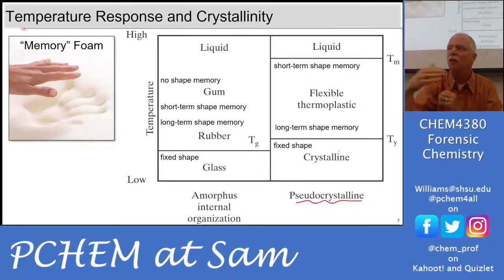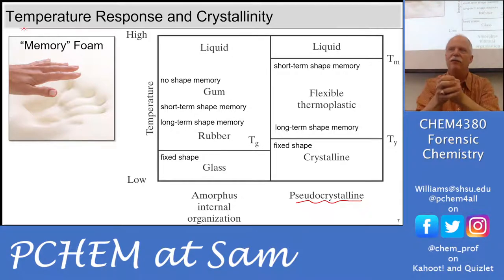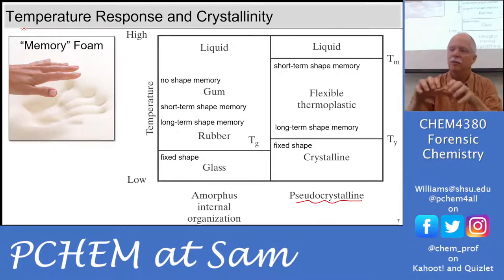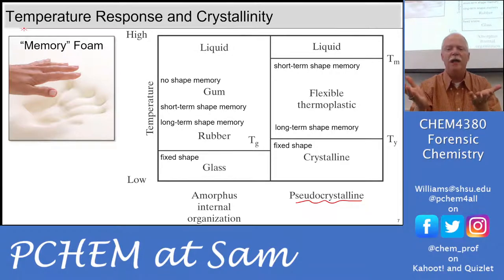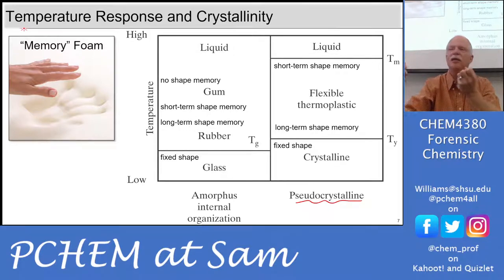The crystallization happening slowly over time is something we'd like to prevent in a lot of plastics — once that crystalline phase starts to grow, it becomes very rigid. We don't want rigid plastics because they crack. This is the mechanism that causes dashboards to crack: over time the dashboard polymers align and grow crystal phases, like chunks of gravel held together by stretched plastic, and cracks develop around the rigid crystalline regions. The crystalline phase pulls so hard on the flexible regions that they start to split — this is called a stress crack.